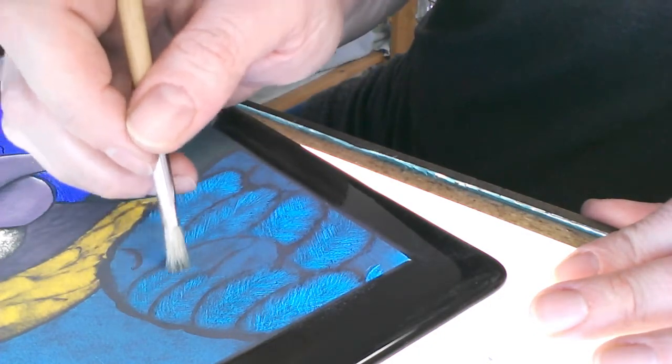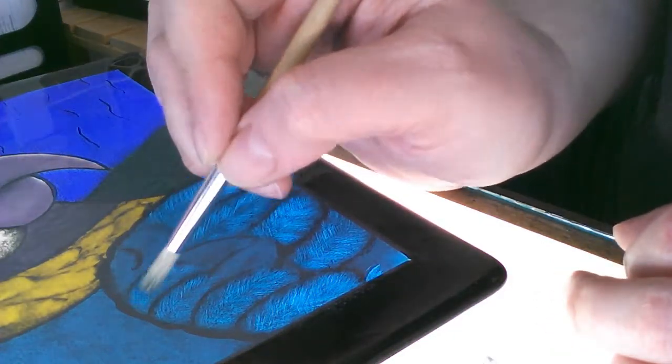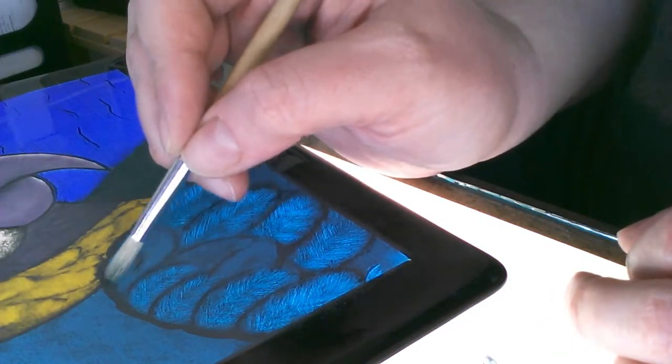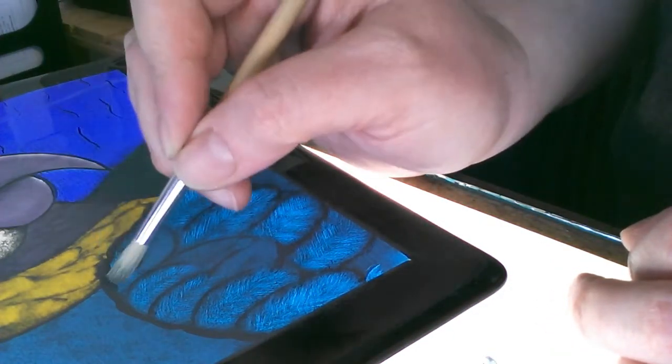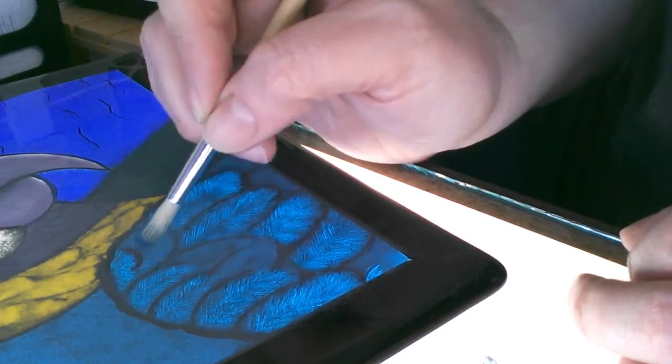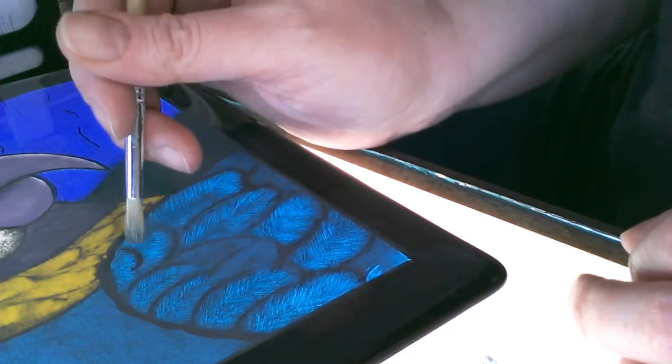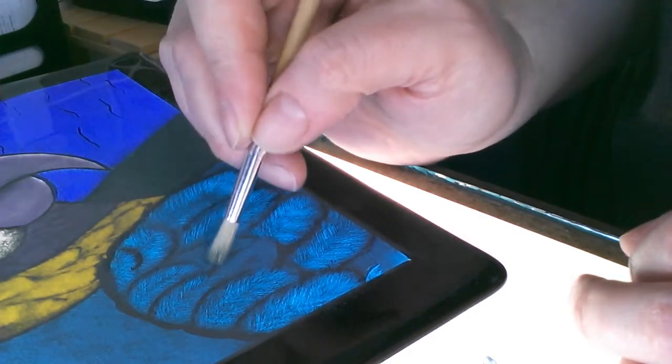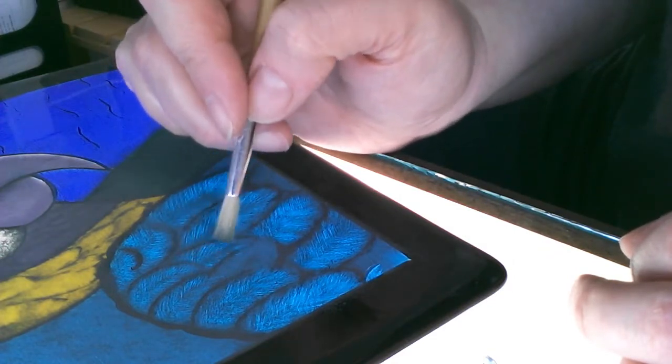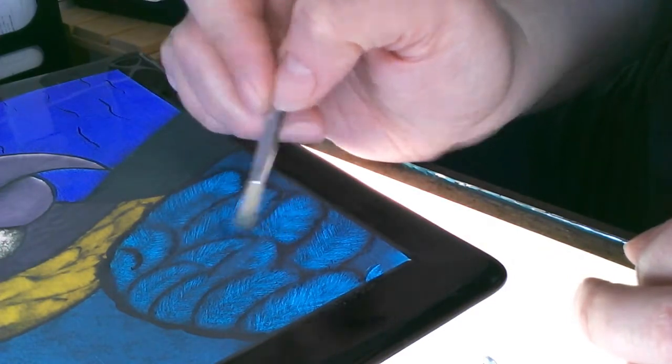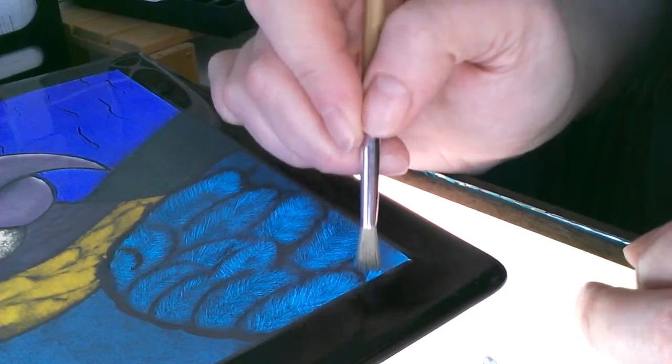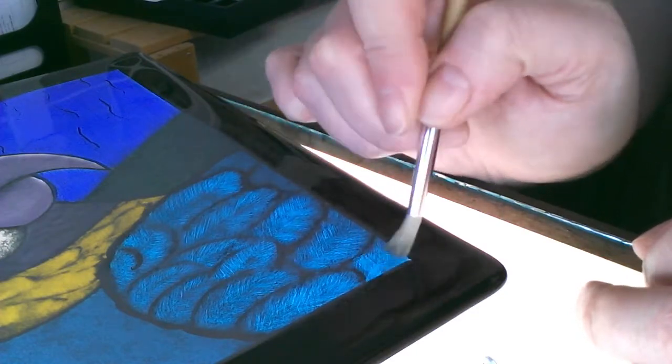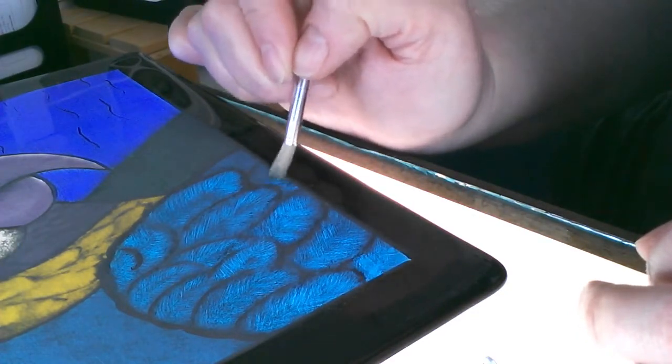Now the paint is generally worked in single layers, and once it has been manipulated or created the effect we're looking for, it's then fired onto the glass in a kiln at temperatures of around 650 degrees. This sets the paint and allows us to build another layer of paint on top without undoing the previous layers we've already done.